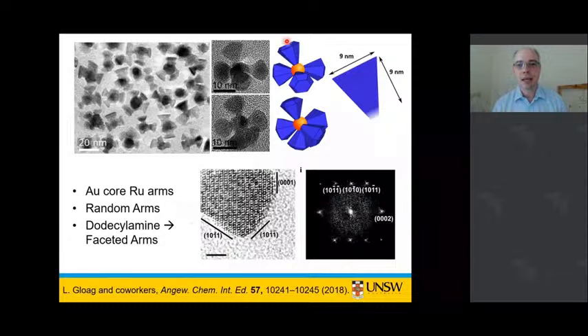Okay, and then we can end up with these beautiful structures. As I said, you have these gold cores, and then you get your ruthenium arms, your ruthenium branches growing off the gold cores. And the other important thing that we do in the solution is put in some dodecylamine. Dodecylamine is a surfactant that binds very strongly onto ruthenium. And it's good because it binds strongly, so it stabilizes these low-index facets we're after. So that's our surfactant that'll bind and stick to these low-index facets and stabilize them.